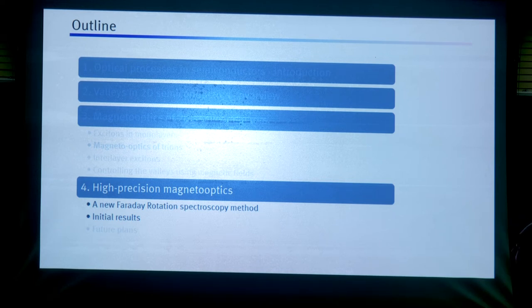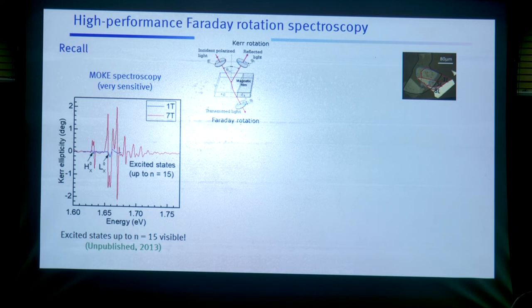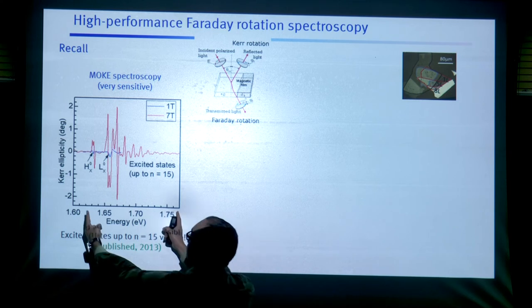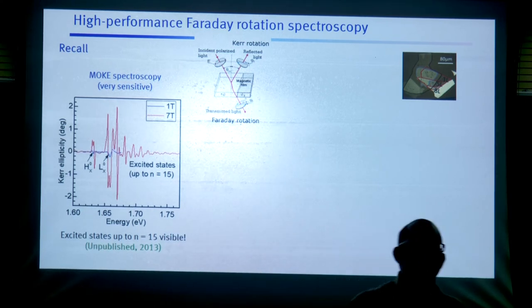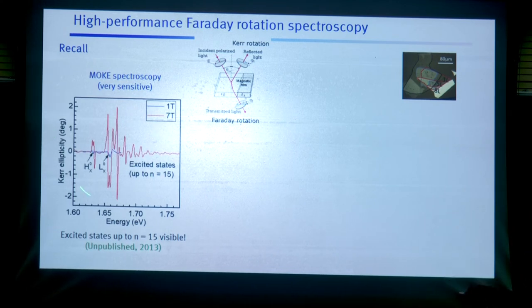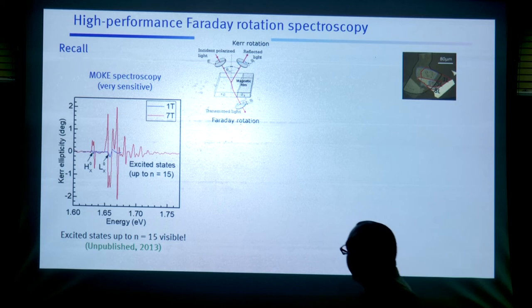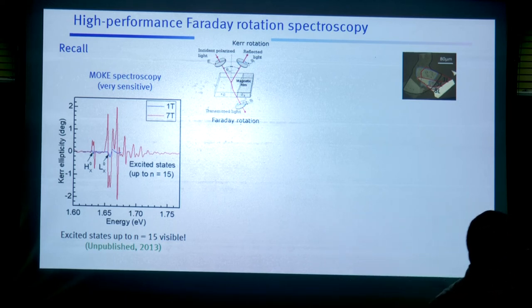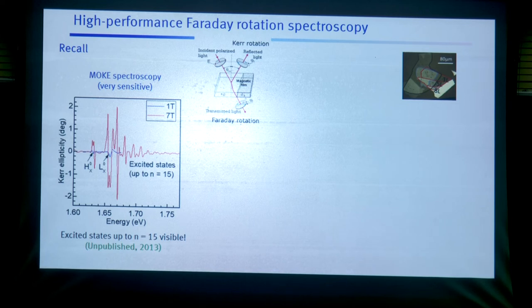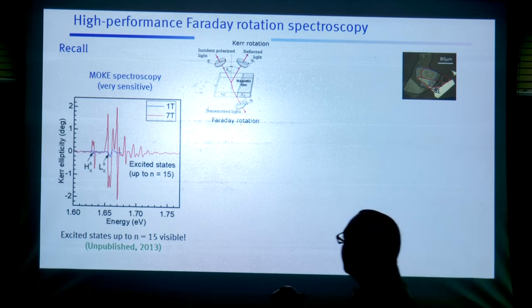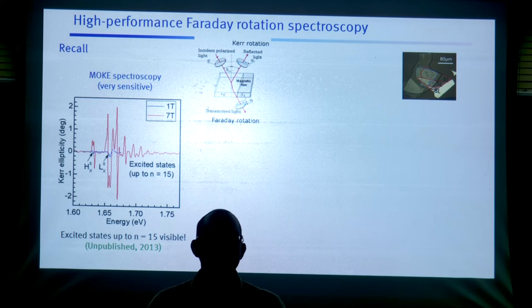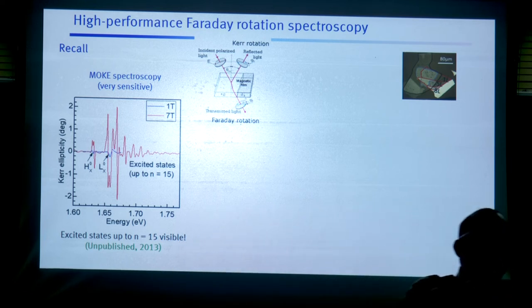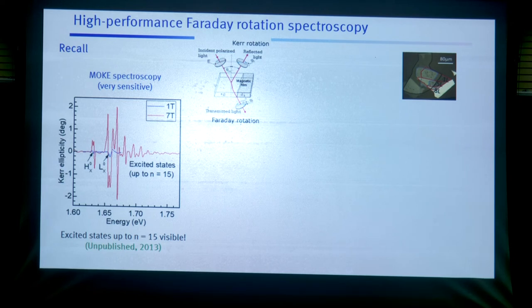This was a new Faraday rotation spectroscopy method. It was required because of the following reason. When you do such a spectroscopy, such as Kerr spectroscopy or Faraday spectroscopy, which I talked about earlier, to take one spectrum you actually have to wait for 4 or 5 hours or even 10 hours. Now you have to keep your sample stable in the cryostat for 10 hours. If you are working with a two-dimensional material in a cryostat, the spot size is of the order of a micron, and if this material moves by a few tens of nanometers, we notice great differences in the signal from various locations because of various non-uniformities in the layers and so on.